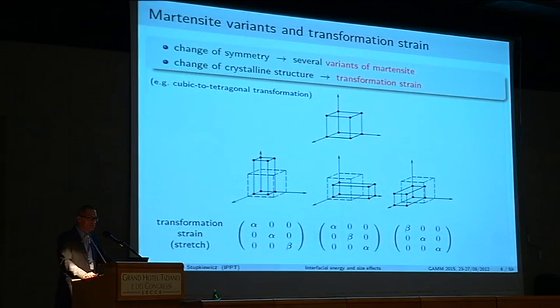So because we have the change of symmetry, there are several variants of martensite. The change of symmetry induces the multiplicity of variants, and here you see an example of a cubic to tetragonal transformation. If you take a cubic unit cell of austenite, you can elongate it along three axes so that you get a tetragonal unit cell of martensite. So you have three variants in that case, but don't be misled. There are other alloys, other transformations, for instance, cubic to monoclinic, where there are 12 variants like that.